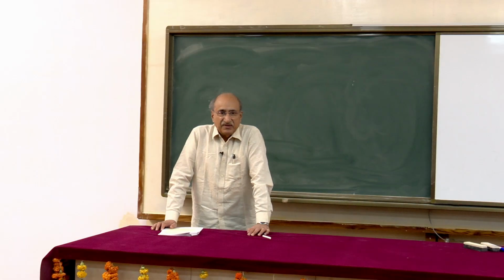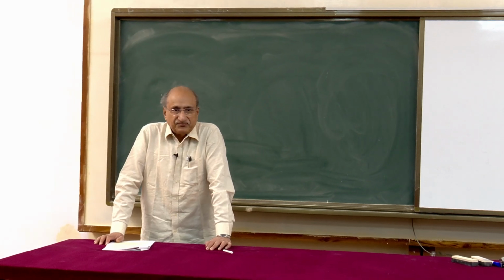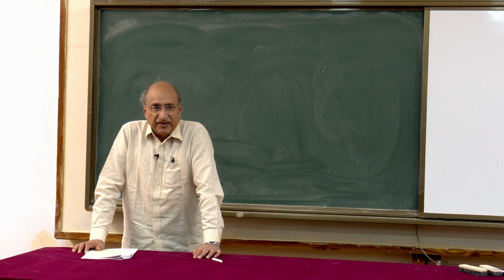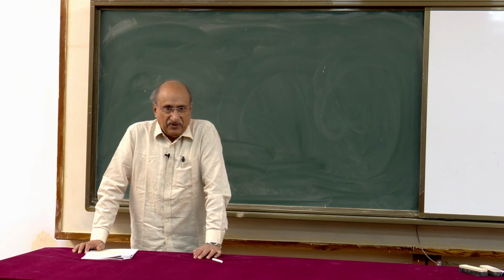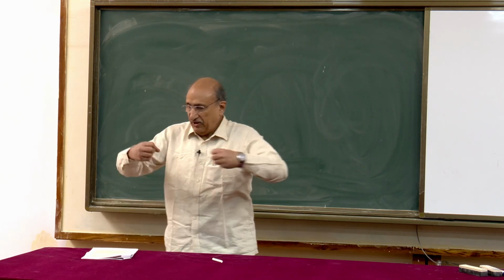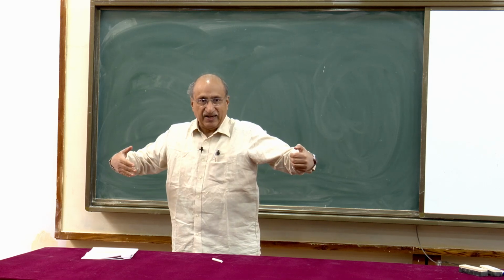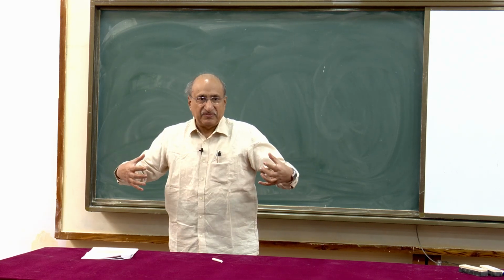In the superexchange interaction, if the angle is more, then the interaction is more, right? Yeah, if the angle is 180 degrees, that's the most ideal. So I did not understand. So for example, if these two ions are here and oxygen is in between, and they are on a straight line, at that time there is a maximum interaction.